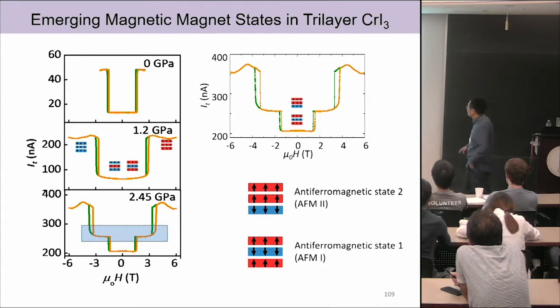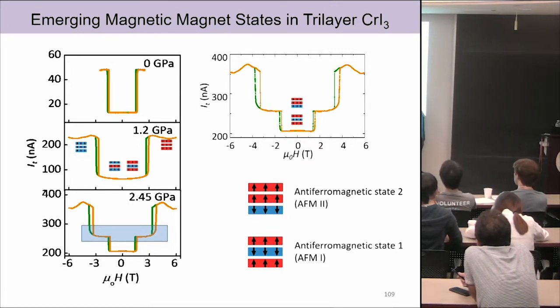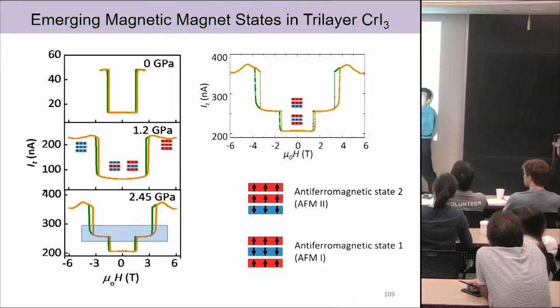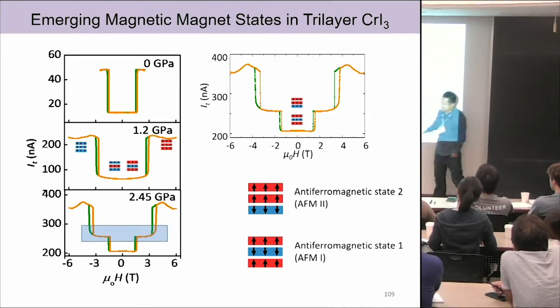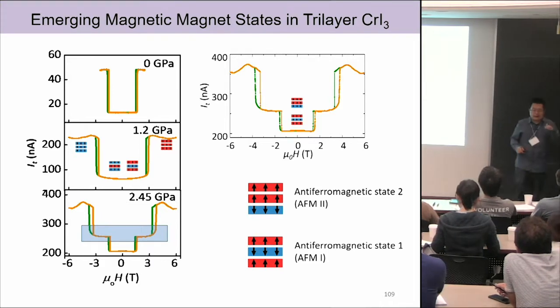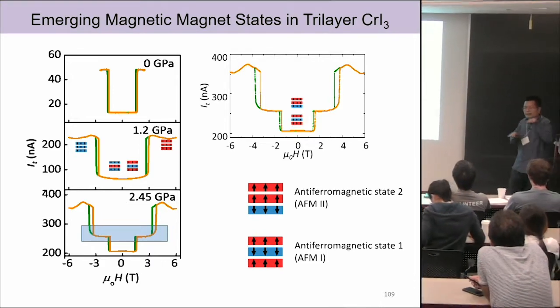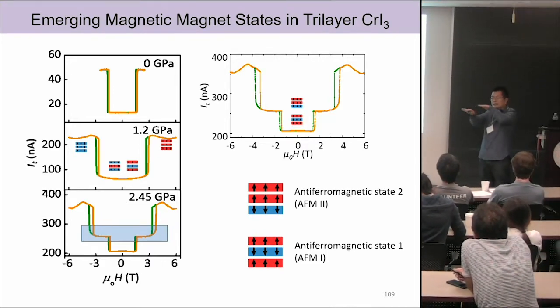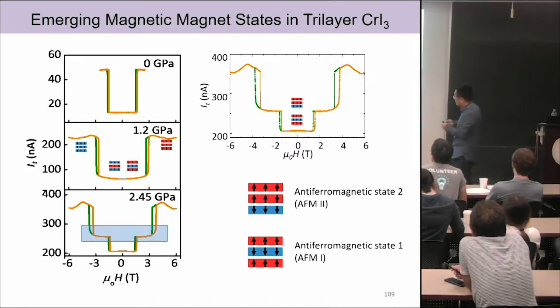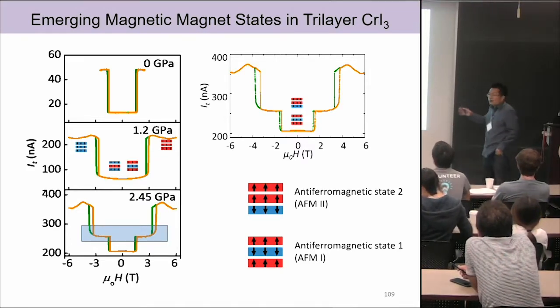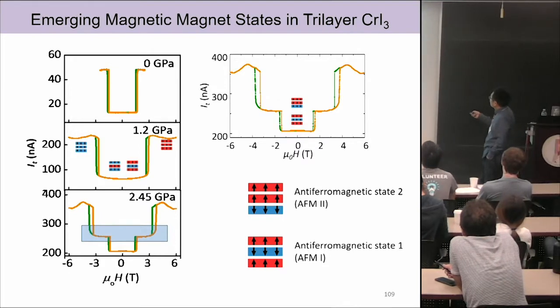So what you can think of is, if it's just a bilayer, the system has already become ferromagnetic. Think about the bilayer I just talked about. It's ferromagnetic. But now I just add another layer to the bottom. So it means that for the bottom layer, the layer sliding hasn't happened, but for the top layer, there's already layer sliding. The stacking already changed.